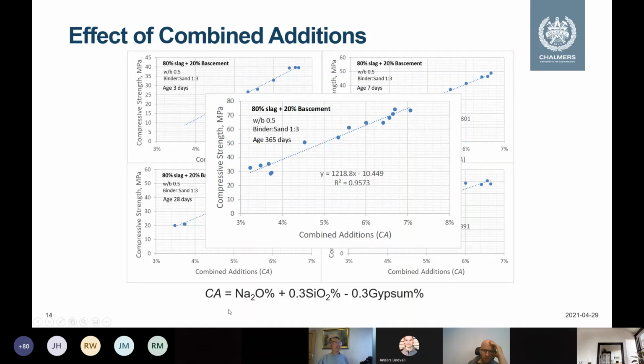And this correlation, we can express it by this equation, a combined addition. So we take sodium content as 1, and then silicate content is 0.3, meaning that the contribution to the strength by silicate is only about 30% of the alkali content. And gypsum is negative, a 30% negative contribution to the strength. We know that gypsum has low strength, so it negatively contributes to the strength, but positively contributes to the shrinkage reduction. I will show that later on.